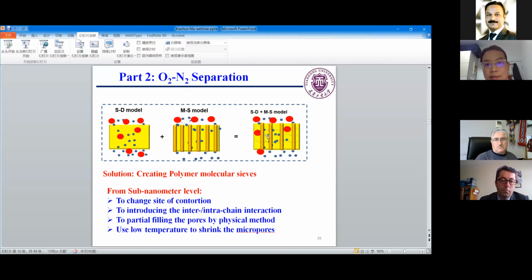But PIMs are different because they contain both. They have the solution-diffusion mode, but they also have pores. These pores are irregular, so they can transport the gases, but they cannot efficiently separate them. As a result, this kind of PIM has very high permeability but modest selectivity. So how to further improve the selectivity of these membranes is the target we want to reach, while also keeping their high permeability.